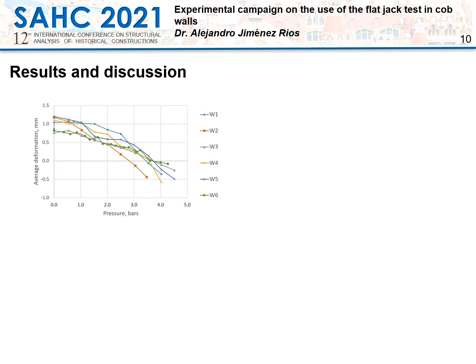After applying a series of coefficients related to the area of the cut in the wall and to the manufacturing of the flat jacks, a mean value for the dimensionless geometrical efficiency constant was obtained as 0.48 with a standard deviation of 0.0427.